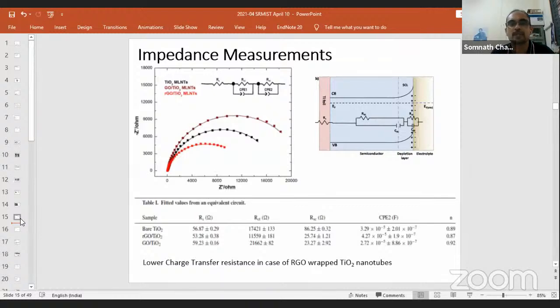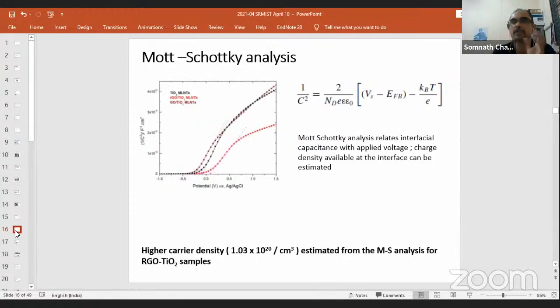We did impedance measurements, which showed that the charge transfer resistance across the semiconductor-electrolyte interface, where the electrolyte is the pH-controlled water, actually reduced. But here I should mention one thing: this is not only graphene, it was technically graphene oxide. Since we were buying functionalized graphene oxide commercially, we could never get pure graphene around TiO2. Whatever we did, there was some oxygen functional group. Later we realized that's not a problem. Even if we wanted pure graphene, since there is oxygen in our TiO2, that oxygen will anyway be attached to graphene. So what we call is the graphene oxide wrapped TiO2 nanotube.